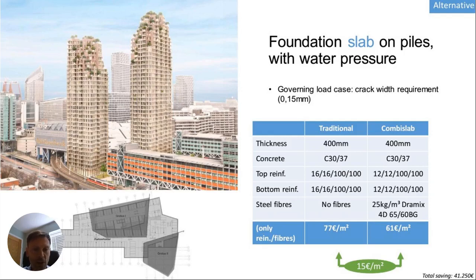Now our alternative solution was a combi slab, so it still had traditional reinforcement in there, but it was the same slab depth, same concrete grade, lighter meshes, and 25 kilos per cubic meter of Dramix 4D. What you got from this was still the required 0.15mm nominal crack width that the solution needed. Okay, but you can see the cost differential was 15 to 16 euros per square meter cheaper by reducing the amount of rebar and adding steel fibers.